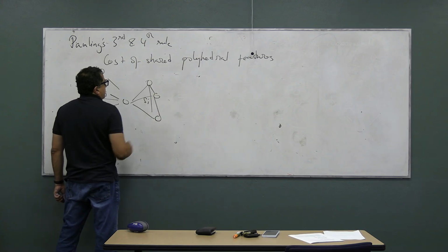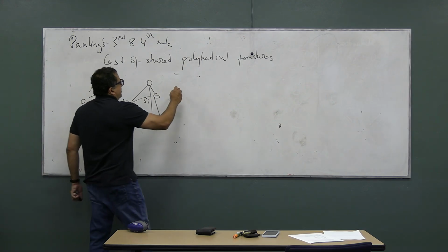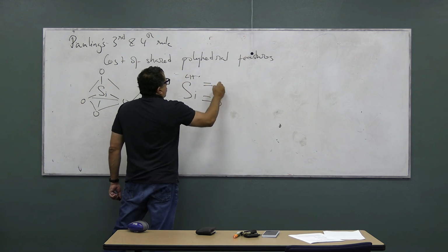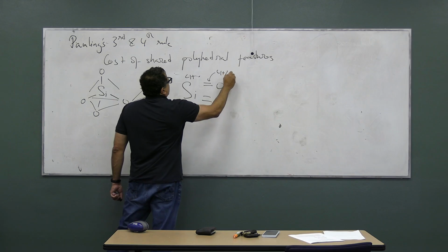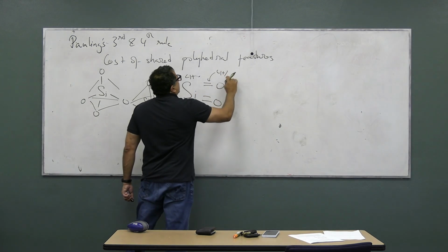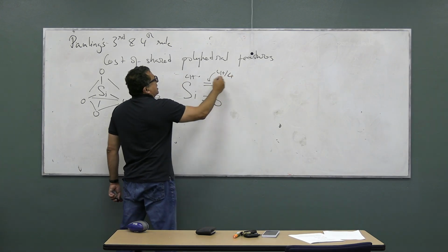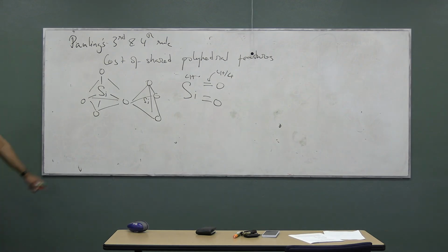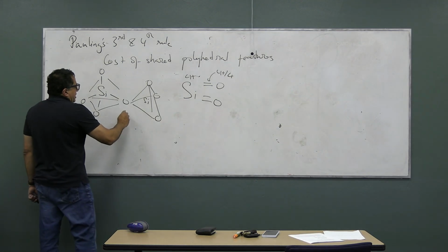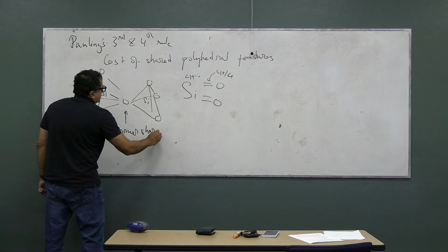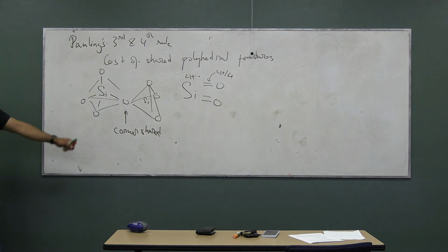2 other silicons. So again, if I write out the electrostatic valence, it's silicon 4 plus over 4 oxygens, so 4 plus over 4, and 2 times 4 plus over 4 is 2. So this oxygen is corner shared. Corner shared. It's called polyhedral corner sharing.